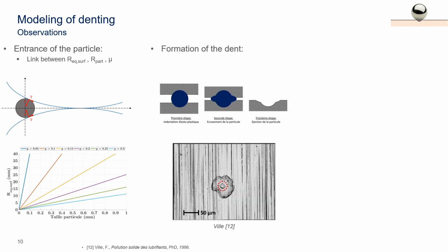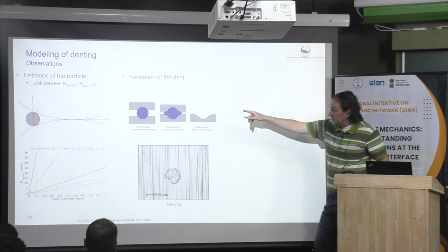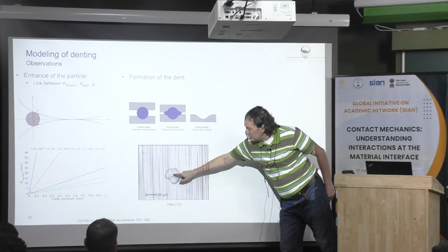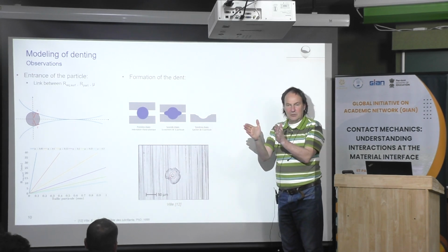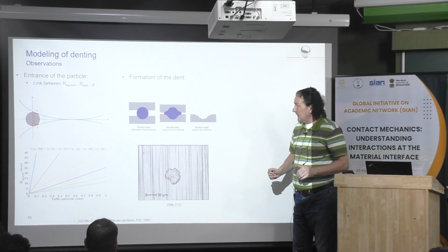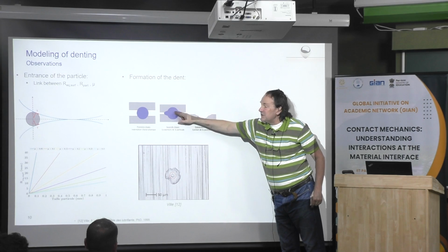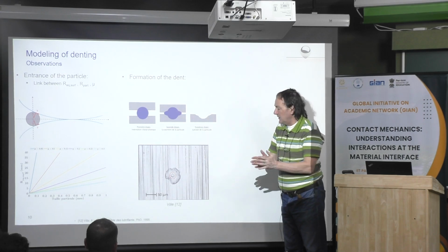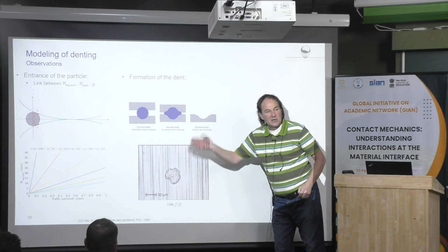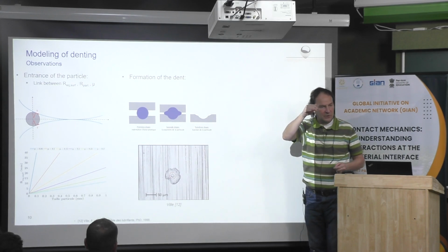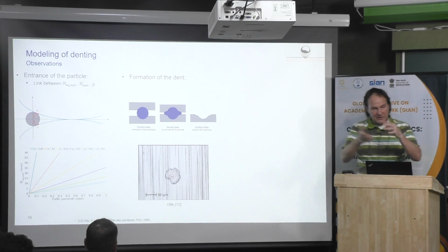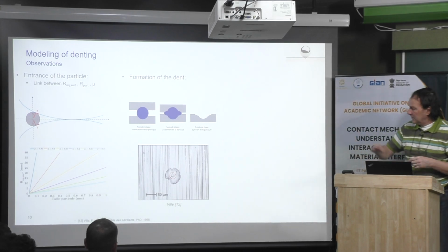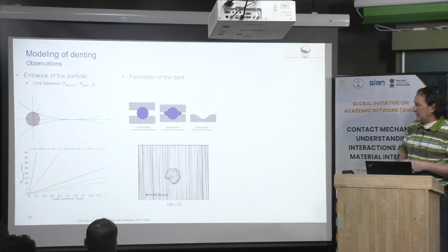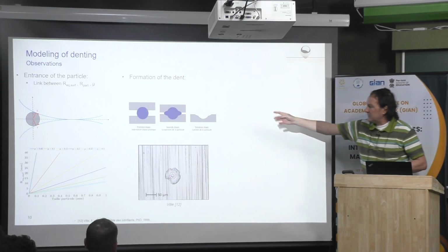Okay. Now, this is what I said before, some kind of flying saucer shape. At the beginning, on the left, you produce the small dent on both sides of the contacting surfaces. And after a while, because you hit the particle, it starts to flow very quickly, and then you have this type of shape, and it corresponds to the particle you have shown before. Maybe not the same particle because there are many particles, but typically we had many dents like that and many particles as I presented before. And then when you remove the particle, you have a dent, in fact.